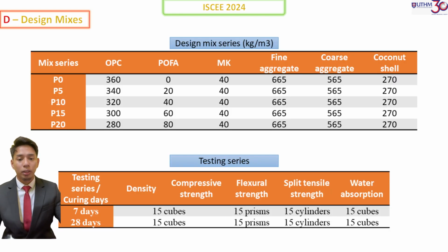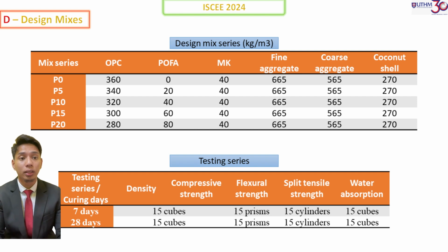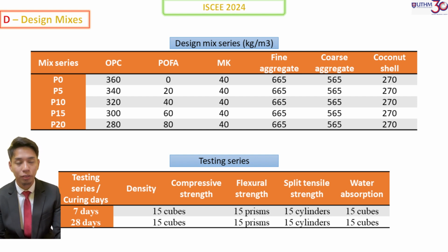So this is the design mix. P0 is 0% of POFA, P5 is 5% of POFA as a cement replacement, P10 is 10%, P15 is 15%, and lastly P20 is 20%. For P0 is 0 kg of POFA, P5 with 5% of POFA is 20 kg of POFA. This table is for 1 meter cube. For coarse aggregate, 50% is used, which is 565 kg per meter cube, and coconut shell 50% is used, which is 270 kg per meter cube.